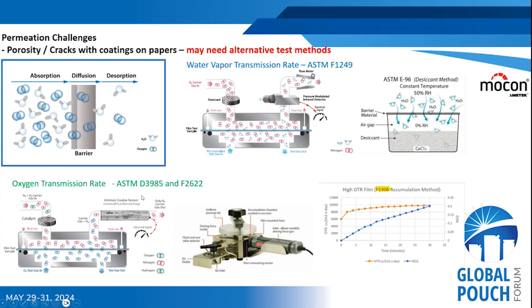So the common test is D3985. If you have higher transmission rate samples, which coated papers are, there's F2622. This utilizes a different detector. It's still an oxygen-specific detector, but it's for higher levels of oxygen that you often see with coated papers.